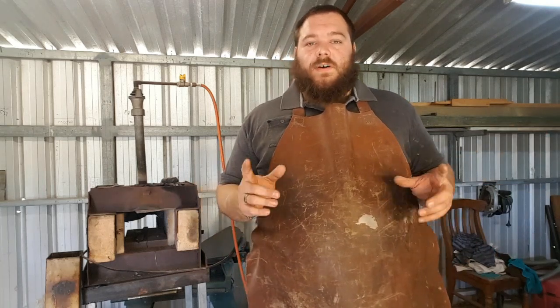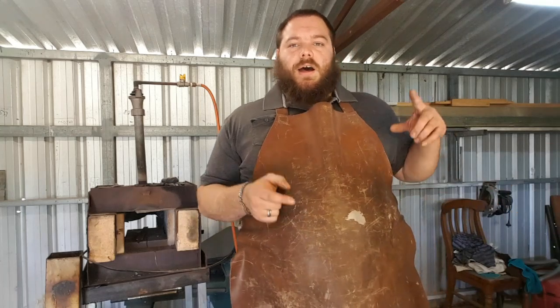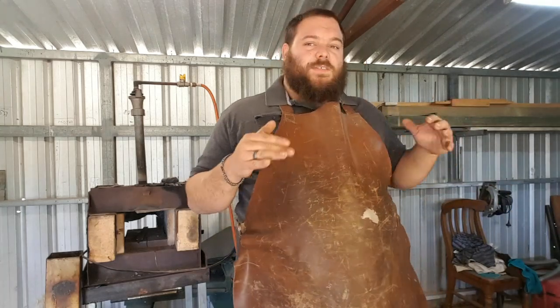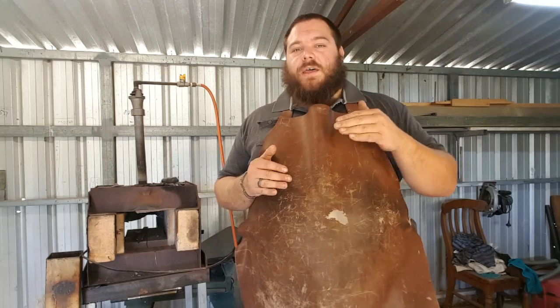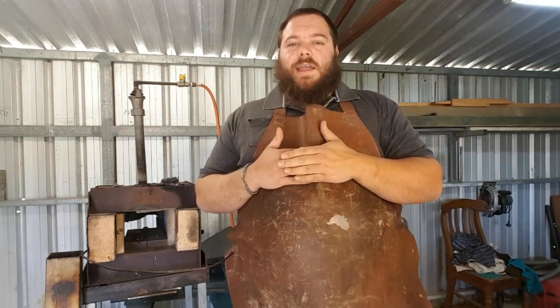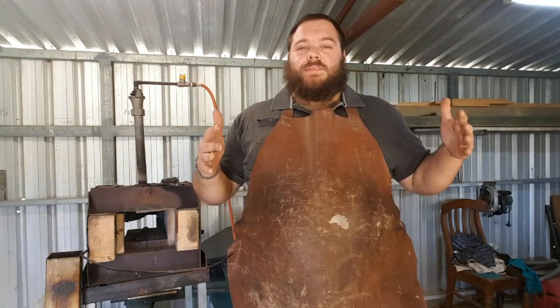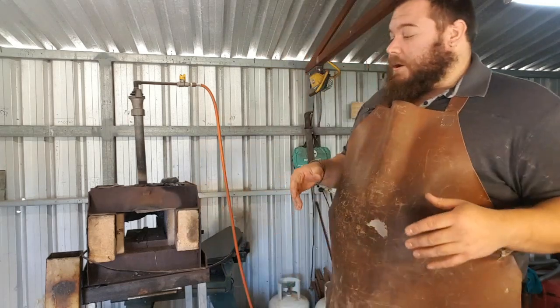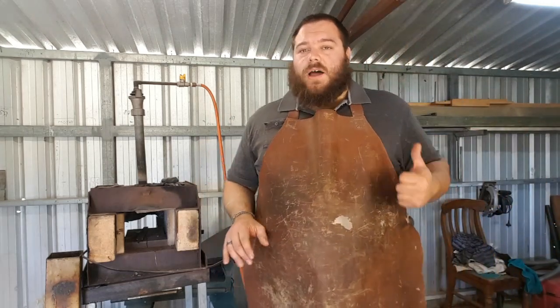I went for a water quench, I believe, in the video. If I didn't, I actually re-quenched it in water afterwards, just to get that super high hardness, because the faster you get it below the martensitic line, the more martensite forms, and the more martensite that forms, the harder it is. So, water is a viable option.